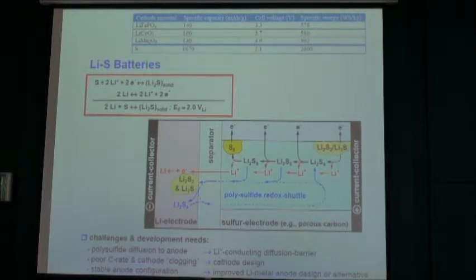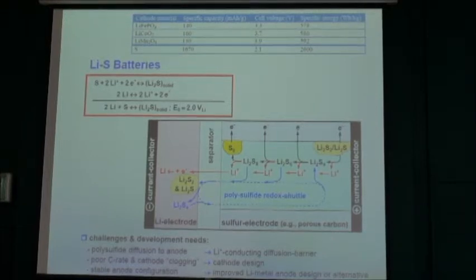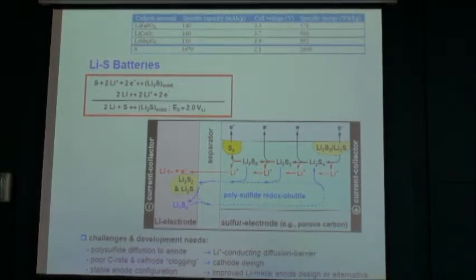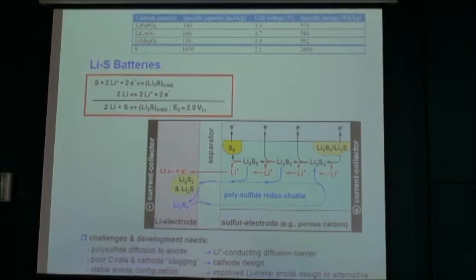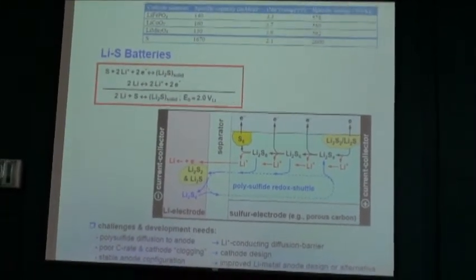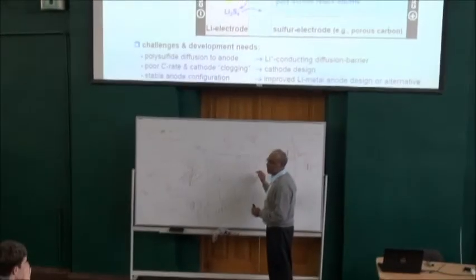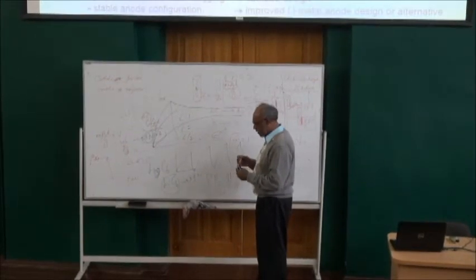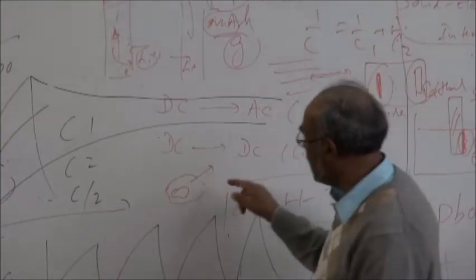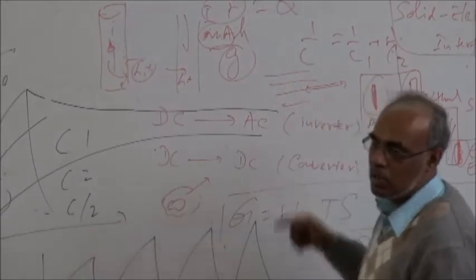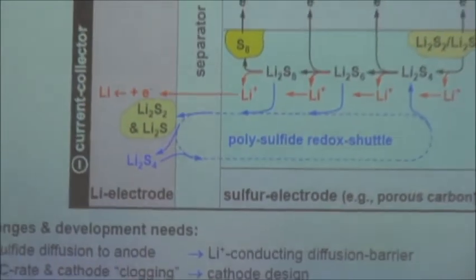When you discharge, it goes from Li2S back to S8 again, so it becomes what's called polysulfide shuttling. The problem is the dissolution of these intermediate polysulfides. So how do you avoid this? What we try to do is wrap the sulfur with graphene. If I can wrap sulfur with graphene, the polysulfide cannot come out; it can be contained. That's something we have been successful with, because the electrolyte can still reach the sulfur, but polysulfides cannot come out. That's our strategy.